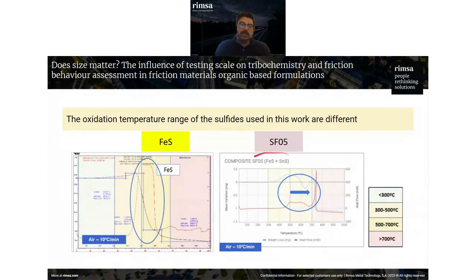What you see here is a TGA, DSC, and what you see here is how the iron sulfide reacts with oxygen to get oxidized. This is something that happens between 400 and 600 degrees, and in the presence of oxygen, of course. Instead, for this composite, we call the SFO5, you see the TGA, the DSC, we see that the reactivity starts at around 450 degrees with the oxidation of the iron sulfide, takes place up to 700 degrees, and then we have the oxidation of the tin sulfide to tin oxide. So two different oxidation profiles, two different temperatures where this oxidation takes place.